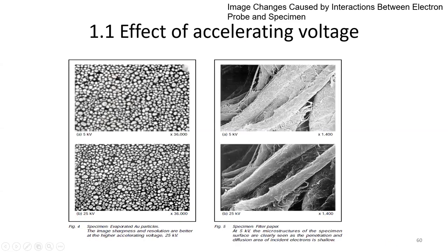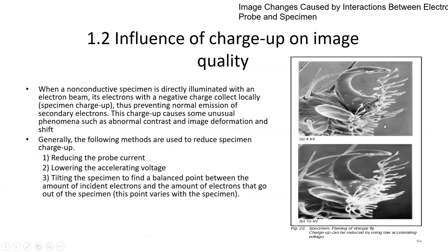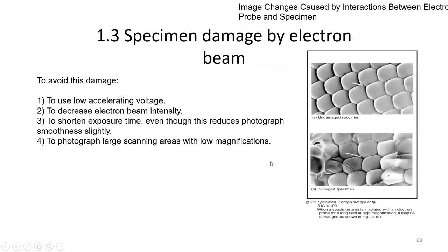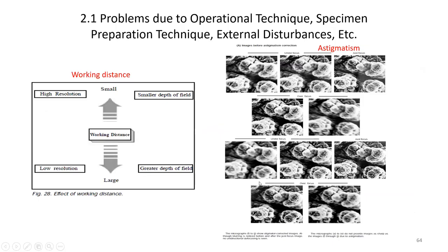Again, here is the same thing. 5 kV gives you much more detail. And this is what charge up is. If you have charge up, you have unequal brightness and contrast in your specimen image. This is beam damage. Sometimes if the electron beam overexposes the sample, you destroy it.